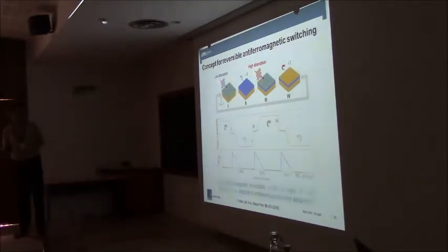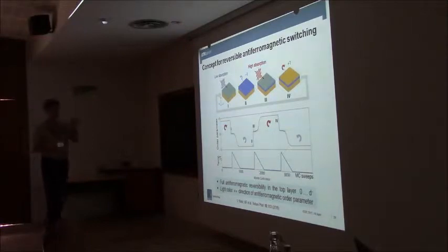So we introduced two-color switching. First, a laser pulse heats the sample to a certain depth, cools down, magnetizes and polarizes in the opposite direction. The second laser is more strongly absorbed, heats up only a top layer, and reverses only the very topmost layer back to the yellow state. The blue laser would again bring it to the blue state. So we switch between yellow, blue, yellow, blue at the surface, depending on whether we take this laser or that laser. Here is the Monte Carlo simulation. So in the computer it works.